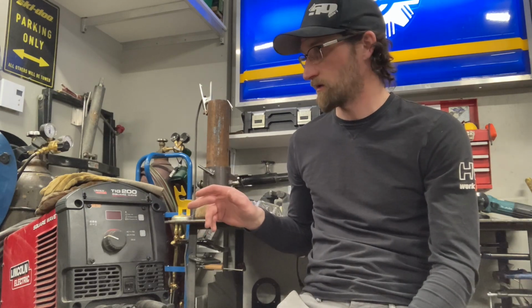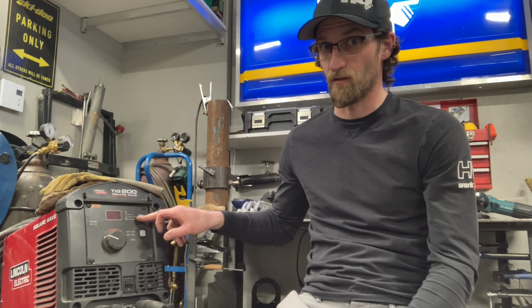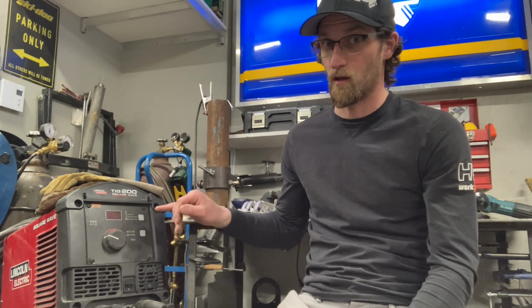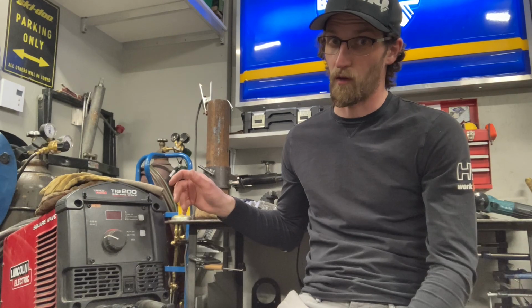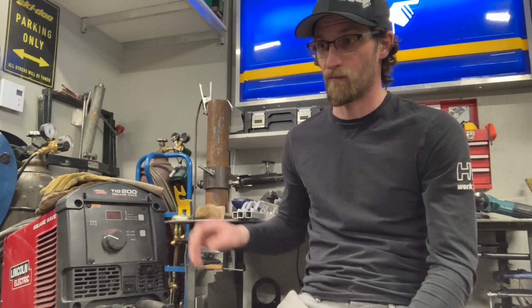I always like to start with my AC balance at about 72% electrode negative. Electrode negative in AC welding is penetrating. Electrode positive is the cleaning. They say that it's because of ionic bombardment from the arc and how it ionizes the shielding gas. So electrode positive is clean, electrode negative is penetrate. I like to start at 72% electrode negative and go from there. If it's dirty metal, you dial it back to 60% or so electrode negative. Usually they never go above 75 electrode negative.